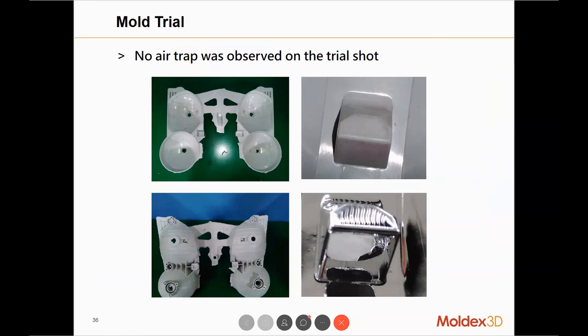So then they do the tool modification, and this is the trial shot result. And as we mentioned before, with a low viscosity, flash can easily be observed in thermoset injection molding. And if we look closely at this small geometry, the final part, there is absolutely no air trap on this small geometry, and the part is successfully filled with a very good surface quality. So TYC were able to solve their real life production issue by our Moldex 3D simulation.